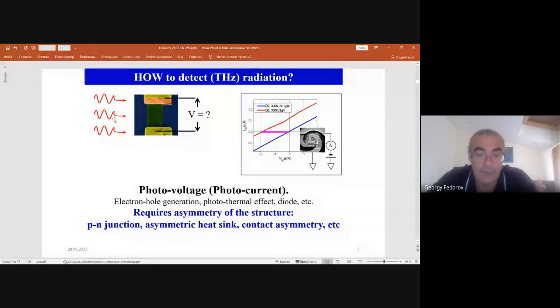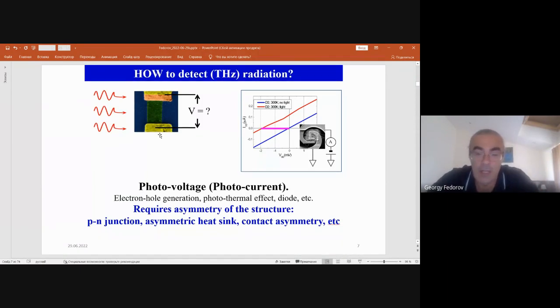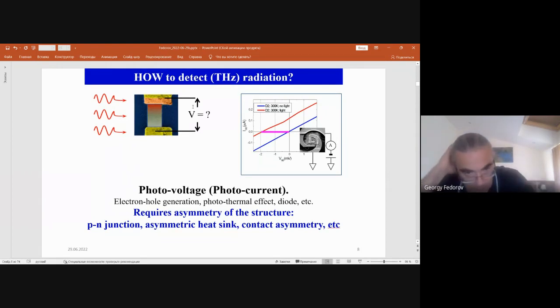Where does it come from? It comes from different types of asymmetry that you built into the structure that you created. It may be parasitic asymmetry, or it may be intentional asymmetry. And this asymmetry will result in different effects. I illustrate here only the photothermal effect, which is the building up of a temperature gradient as a response to the radiation. And this temperature gradient will result in photothermal, thermoelectric power. So the red part here is supposed to be heated more because, for example, there are worse contact properties on this side, right? So that's one of the effects, when asymmetry results in the appearance of a photovoltage.